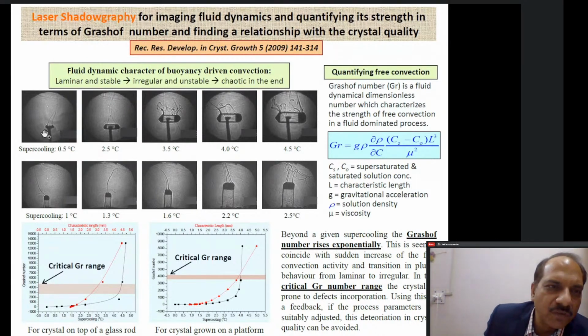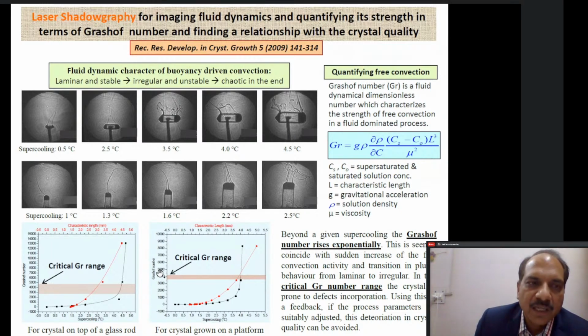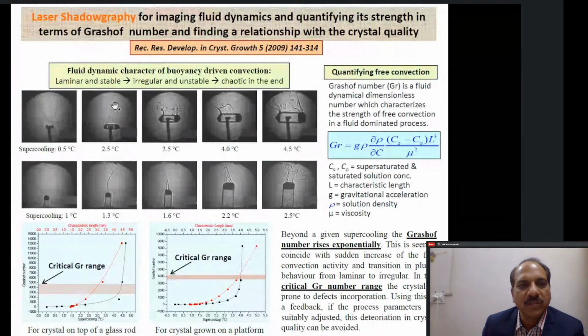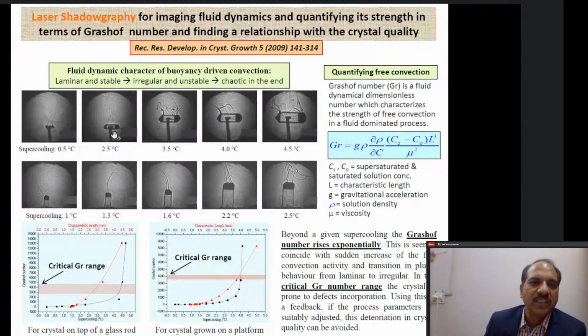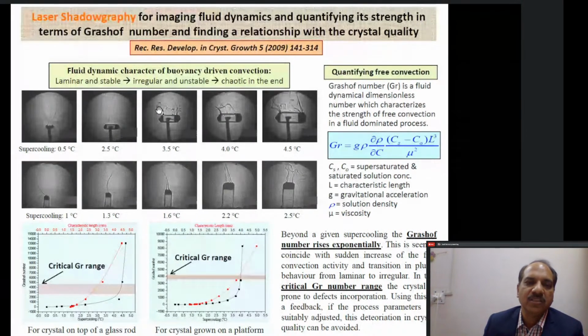And if you see closely, you will see two black lines which are emanating from the top surface of the crystal. These two lines are nothing but the undersaturated solution, because the solute has got deposited on the crystal surface, and that solution which is adhering to the sides or edges of the crystal is now undersaturated, and because of the effect of buoyancy, this undersaturated solution will start to rise up. This undersaturated solution is of different refractive index as compared to the refractive index of the solution surrounding it. So the parallel beam of light passing through gets deflected, and because of which the contrast of the region which otherwise had a uniform intensity changes, and you will see these black streaks, which are nothing but the light from these regions having been deflected to the other region, and here we are seeing a black region. In fluid dynamic language, these are called plumes.